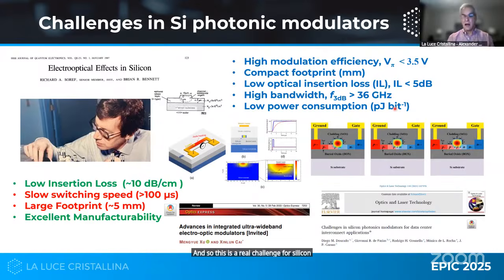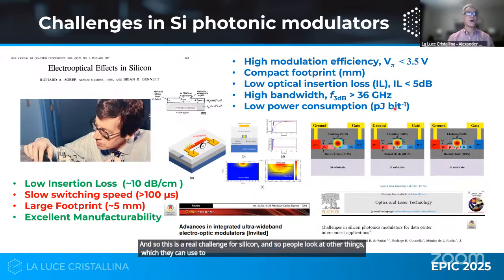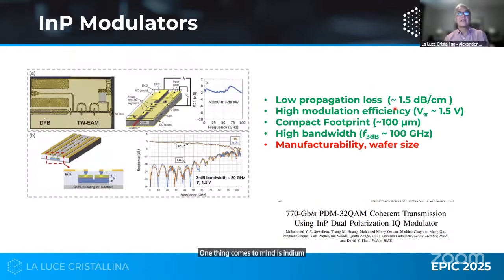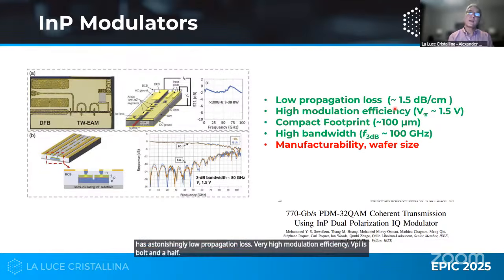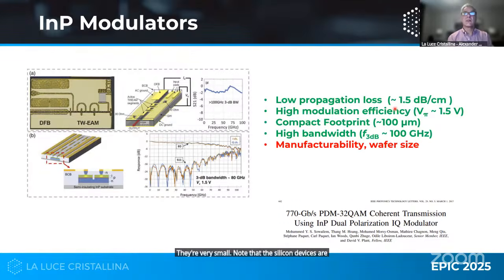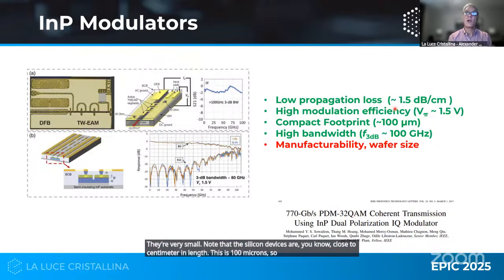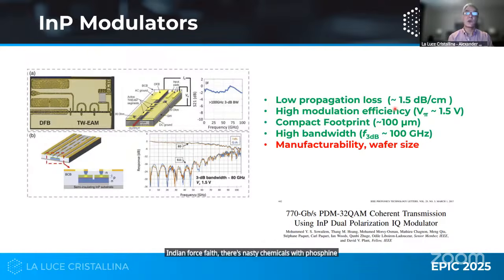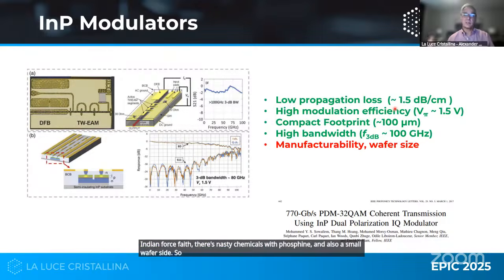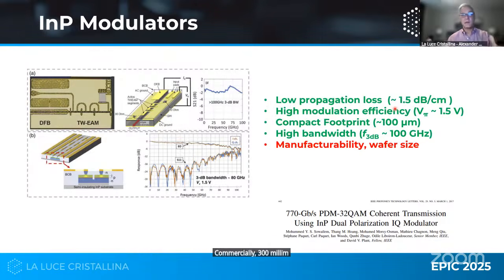And so people look at other things which they can use to modulate. One thing that comes to mind is indium phosphide. The material has astonishingly low propagation loss, very high modulation efficiency. V-pi is a volt and a half. They're very small. Note that the silicon devices are close to a centimeter in length. This is 100 microns, so it's very small. And they have very high bandwidth. The problem is manufacturability. Indium phosphide has nasty chemicals like phosphine, and also a small wafer size. So silicon is commercially 300 millimeters. A lot of it is 200 millimeters. Indium phosphide wafers are much smaller than that.